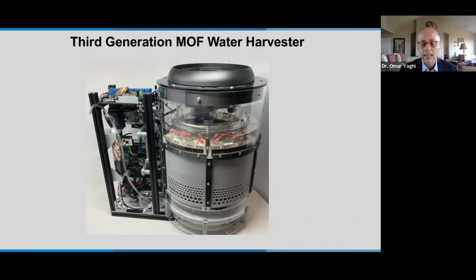Let me repeat that, 100 grams of water, 1/10 of a kilogram of water. And with 100 grams of water that stays in this device for many, many years, every day, you can harvest 4 liters of water, okay? So 4 liters of water a day based on 100 grams of MOF. And that's because the MOF extracts water readily, and you can remove the water from the pores without having to heat to very high temperature. And so you can do many, many cycles.